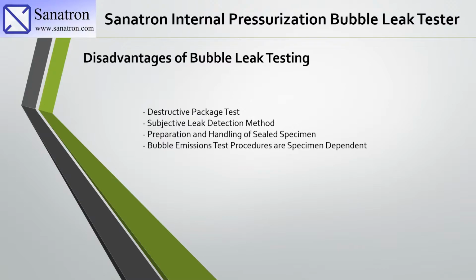And finally, bubble emission test procedures are specimen dependent. So it depends what type of specimen you have. Sometimes you can have small pouches which disqualify them for internal pressurization testing. Sometimes your film can be brittle and you may not be able to perform internal pressurization testing, because as soon as you insert your probe, you will damage the film, create a stress crack, and completely damage the test specimen. So it is specimen dependent as well as operator dependent. Again, those are the disadvantages.